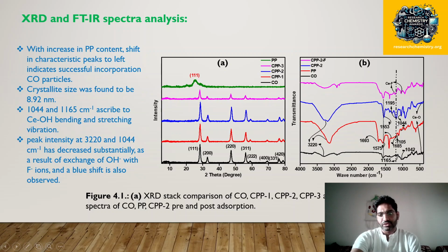So these stretching vibrations, we could see that their intensity has been lowered, which means that successful incorporation of fluoride by exchange of hydroxide ions has taken place. Here we could also see that the OH minus ion, which has a peak at about 3220 centimeter inverse stretching vibration, has sufficiently reduced intensity, which might be due to the successful exchange of fluoride ions with respect to hydroxyl ions. So this tells us the confirmation of the fluoride adsorption in the IR spectra.